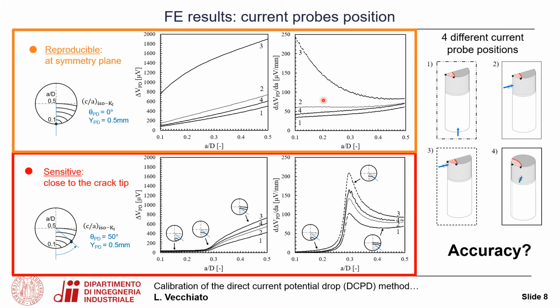It can be observed that in general the considerations are the same, so the sensitivity and the measurability are higher whenever the current probes are also located as close as possible to the crack tip. As in this example, whenever the crack tip reaches the position of the potential drop probes, the sensitivity assumes the maximum values and then tends to the values that they assume whenever the potential drop probes are located on the crack symmetry planes.